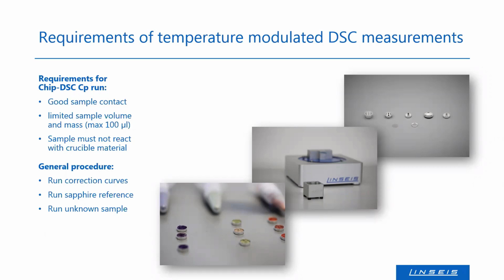Our standard crucibles for the chip DSC, for example, the biggest crucible is around 100 microliters, so everything is okay then. But if you calibrate with a 0.5 millimeter calibration material and want to measure a 5 or 10 microliter sample, for example a polymer with bad heat conductivity, then there will be an error. So you have to make sure this doesn't happen. And of course, a simple thing: the sample must not react with the crucible material. So I think that's clear. If you want to measure gallium, we need different crucibles than our standard crucibles made from aluminum. Of course, you can use alumina, or whatever crucible you can find here.